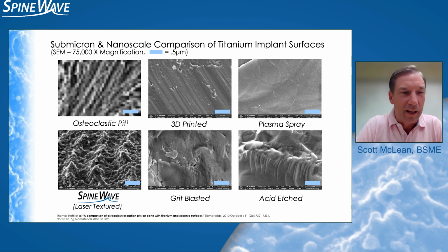Now, I'd love to show you the collagen fibrils in the osteoclastic pit, but the micrograph just doesn't have the resolution to get us down to that level. So you'll have to take my word for it on that one. But the literature that we have and the measurements we've taken, we believe that those little nanostructures do compare very well. And again, the detail on the competitive titanium surfaces is just significantly diminished at this magnification.